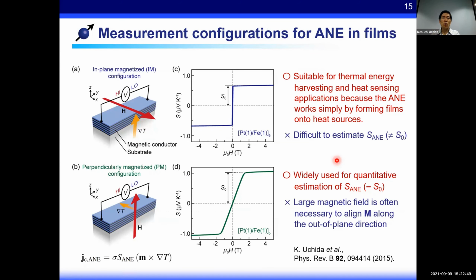The other setup is called the perpendicularly magnetized configuration, where the film is magnetized in a normal direction of the film surface, and the temperature gradient is applied along the in-plane direction. In this case, it's easy to estimate the temperature difference in the sample, and the anomalous Nernst coefficient is usually quantified in this setup. Here is an example of the experimental results of the anomalous Nernst effect in each setup. Here we used iron platinum multilayer film, and as this symmetry shows, the thermoelectric voltage shows an odd dependence on the magnetic field, and when the magnetization is saturated, the thermopower is also saturated. The odd dependence on the magnetic field is a common behavior of all the transverse thermoelectric conversion.